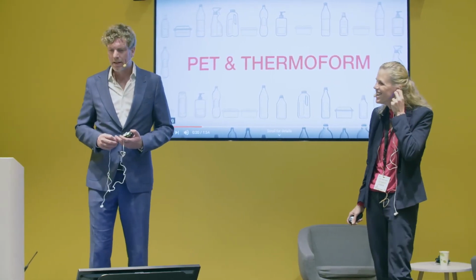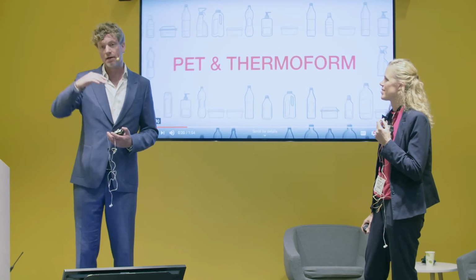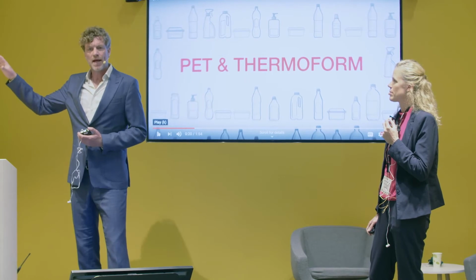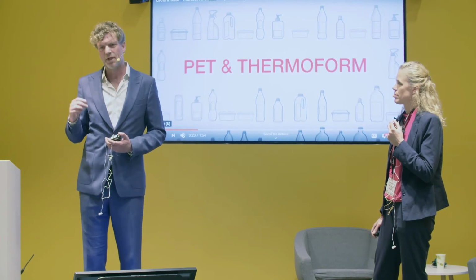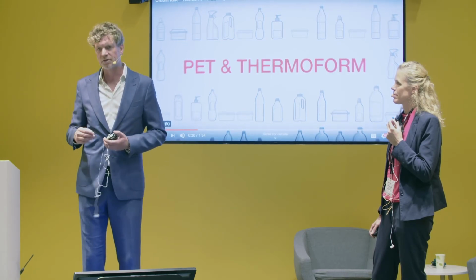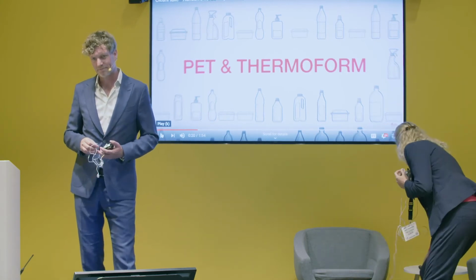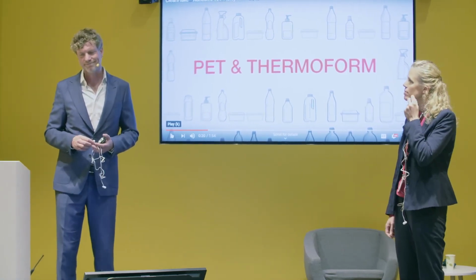What we see is that typically only in PET recycling, all the sleeves that are actually floating, basically all the floating material, also including the caps, will be shipped to a mixed polyolefin recycler. And there you basically are creating a blend of PE and PP with some other materials in between. And it's used for more thick wall materials, big plates, garden furniture, stuff like that. So we consider it downcycling. So it's not fully recycling. It's not near to virgin quality. But for everything that's at the PE or PP recycler, it's discarded.